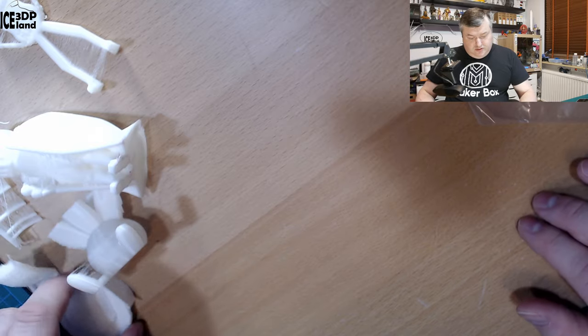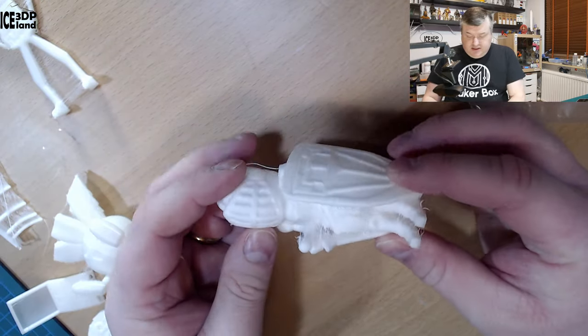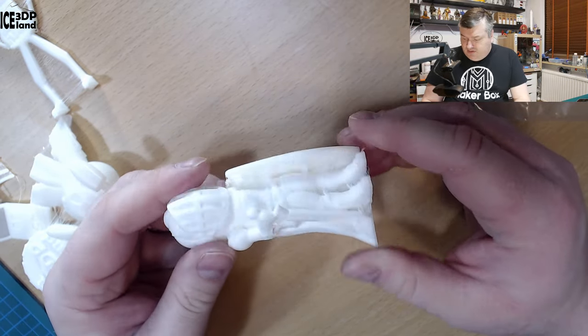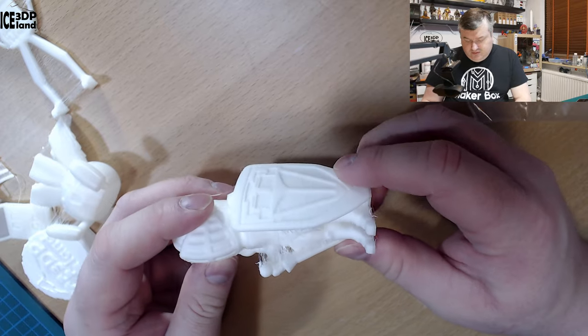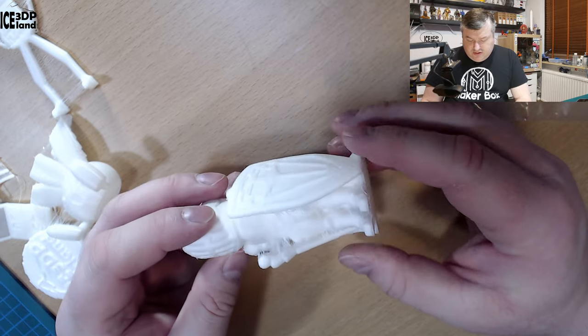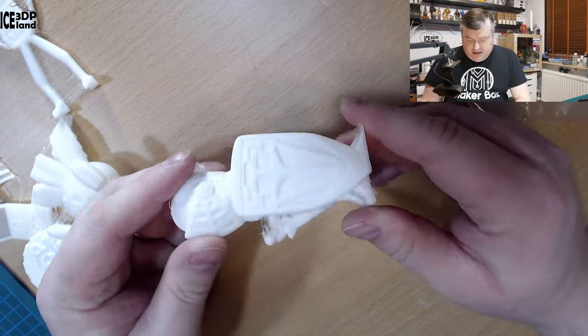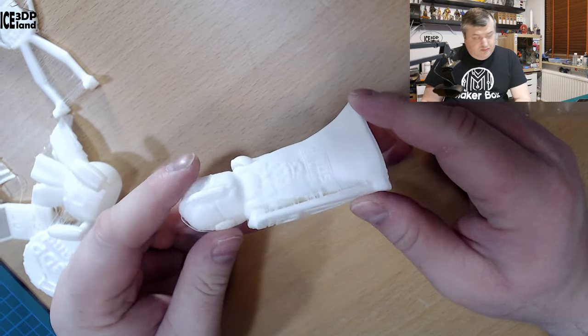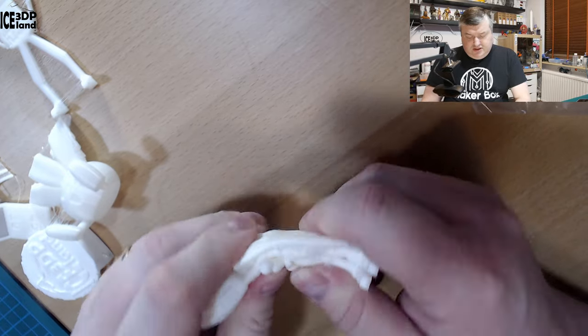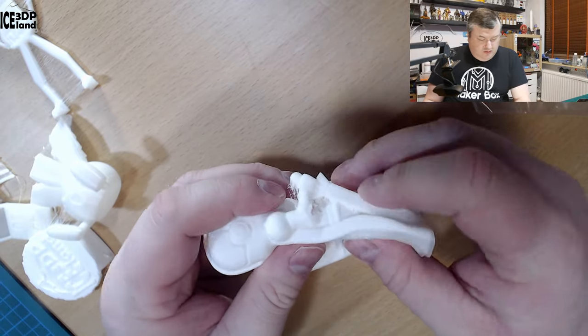Here are my prints — I was playing around with different temperature settings. This one was printed at 215°C, so it was starting to foam a little bit. As with TPU there's some stringing, but otherwise it came out pretty good. It looks like a matte white print and it's quite flexible as you'd expect from TPU.